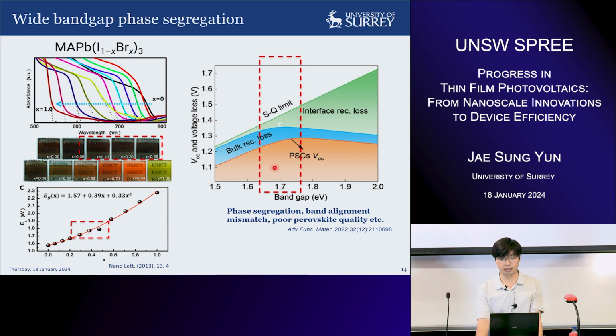gap perovskites. So if you see record efficiency of perovskite material, perovskite solar cells, they are mostly a narrow band gap, which we call around 1.55 to 1.6 eV. So that's where the high performance perovskite solar cell is, and there are many issues related to wide band gap perovskite, which I will introduce later.